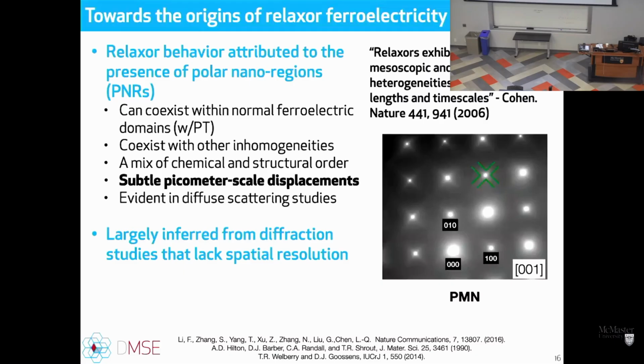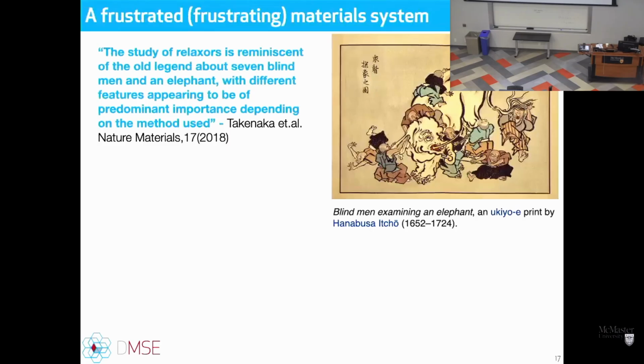So rather than nice sharp diffraction spots, you always end up with these, they look a bit more like butterflies in neutron and X-ray diffraction, hence why they're called butterfly diffuse scattering. But here, this sort of streaking is due to those local effects. And it's largely inferred from diffraction studies. Directly identifying what's changing and where is much more challenging from X-ray than looking at it directly in the electron microscope. But this is why,